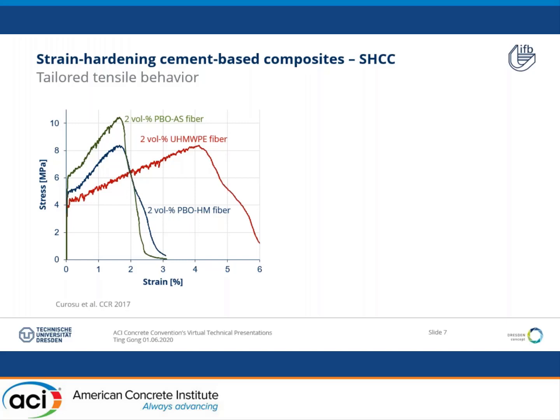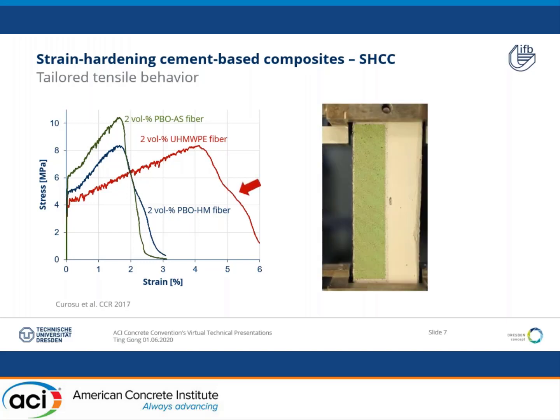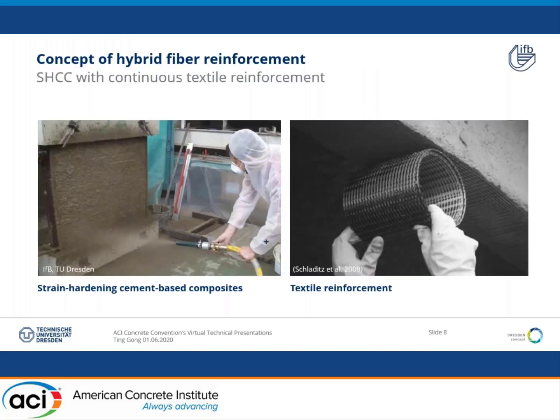For example, a high-strength strain-hardening cement-based composite with short polymer fibers. The material itself is already characterized by its superior ductility with a high level of multiple cracks, as we can see from this video. SHCC with the addition of short PE fiber exhibits the highest strain capacity among the three. What is more, the easy application and good compatibility of SHCC with textile also indicate a promising material design of hybrid fiber reinforced composite, which combines continuous textile reinforcement with the strain-hardening cement-based composite.